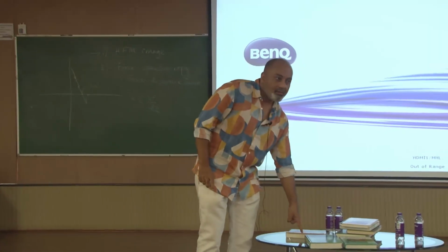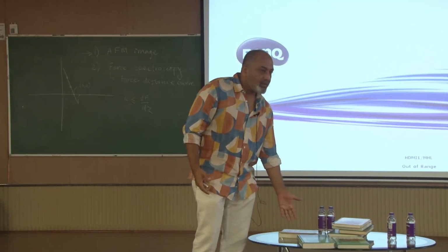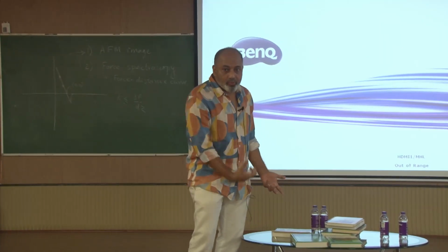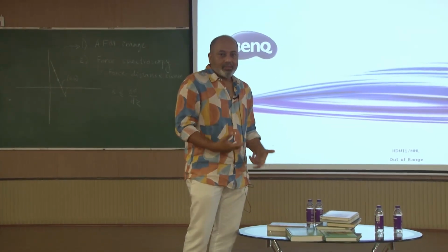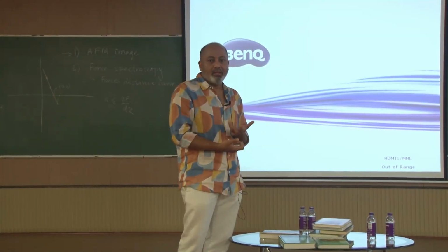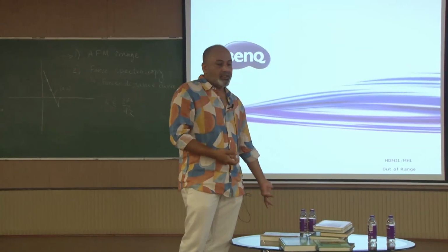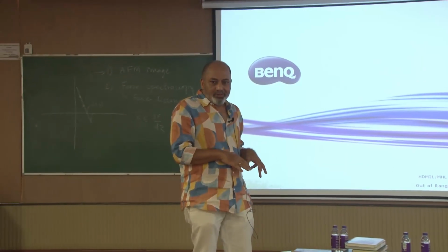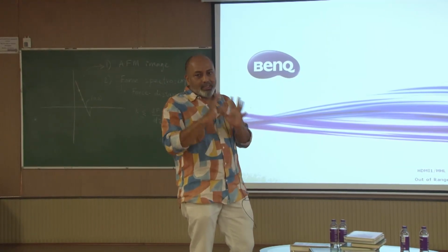Like suppose this is a cell, yeah, and I came with 1 volt, and the cell thickness is whatever, and the load on it is larger than 1. So, now we said that it has to be pushed back by the same amount, that is the thickness of a cell, but the cell's loading behavior is different. For the same amount of deformation, the cell will not give the same amount of force, the cell will not be deformed by the same thing as the glass. So, you pull down by a different amount. Okay. So, it will not only give topography, it can also give the mechanical properties of the material beneath it. Okay. But that is a little more complex.